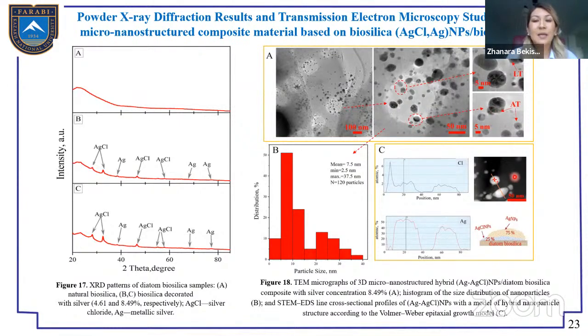And the STEM analysis of one particle showed that it is a hybrid particle, and the nucleation was first the formation of the silver chloride nanoparticles on the surface of the diatom biosilica, and after that it was covered on top with metallic silver nanoparticles, and the model of the epitaxially growing particles.